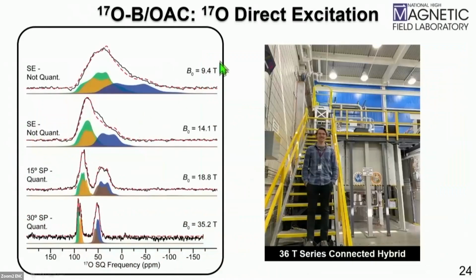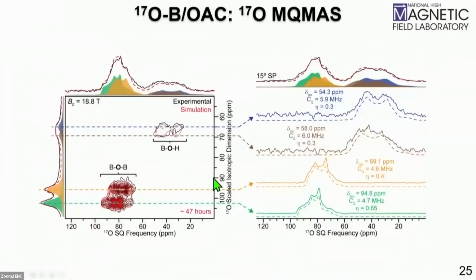So we first recorded 1D oxygen NMR spectra from 9.4 Tesla all the way up to 35 Tesla using the 36 Tesla series connected hybrid magnet at the high field laboratory. Now, we were able to confirm all of our oxygen NMR signals from this very beautiful MQMAS at 18.8 Tesla that Dr. Ivan Hung recorded. And what we see is that there are two main groups of signals, which correspond to the hydroxyl groups and the bridging oxygen atoms. Now, what is really interesting, you can see there's clearly two unique bridging oxygen NMR signals that have very different quadrupolar asymmetry parameters.